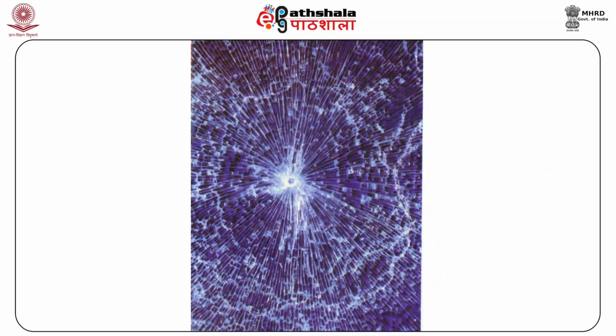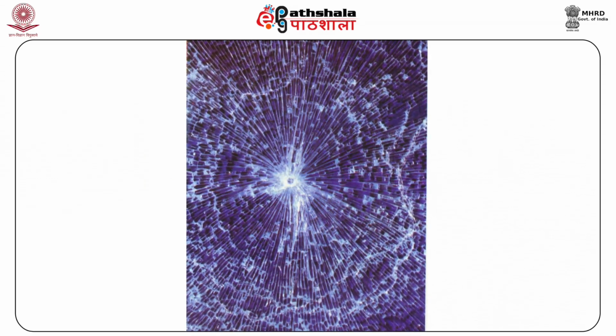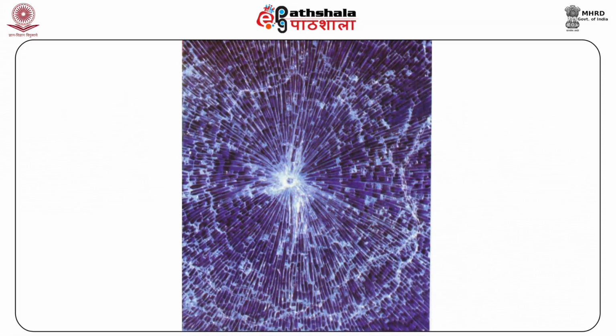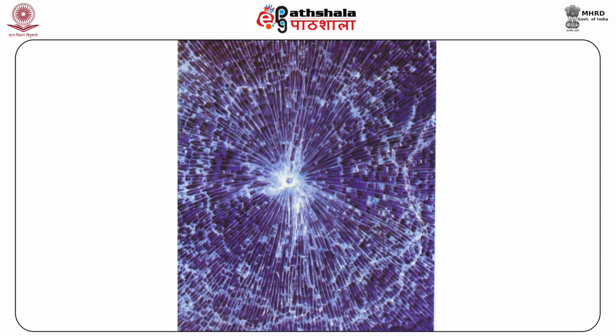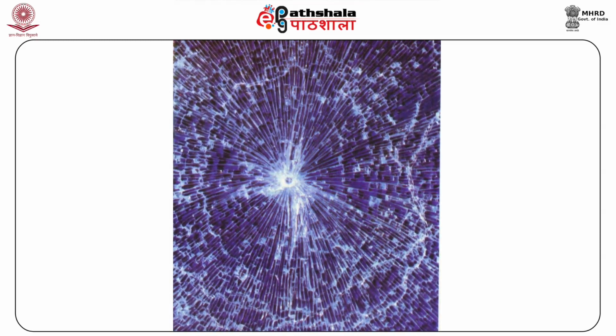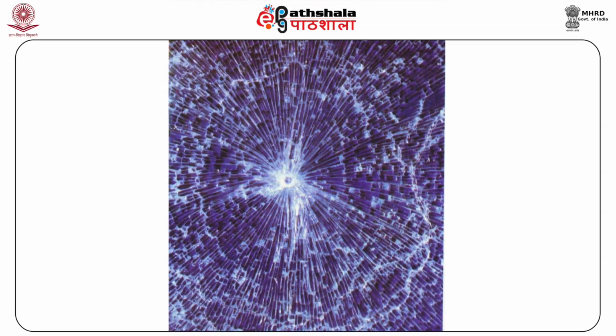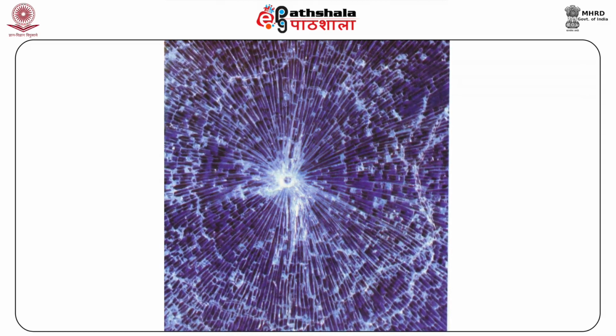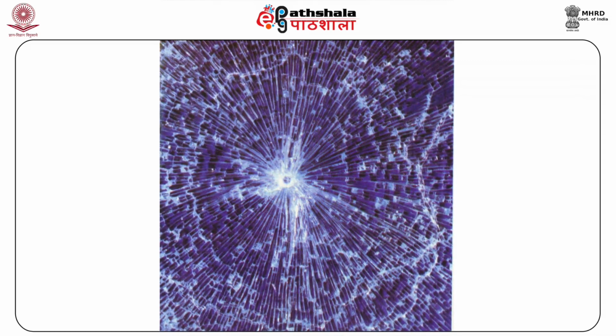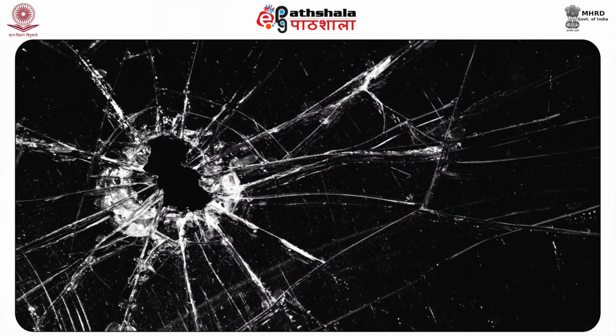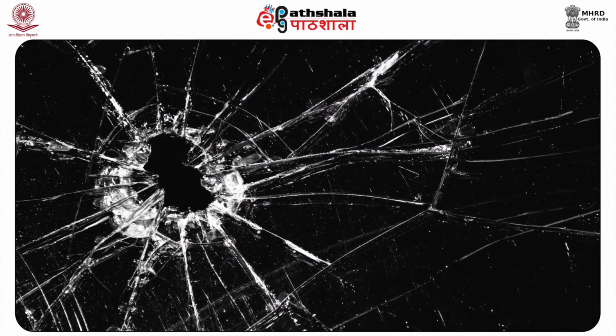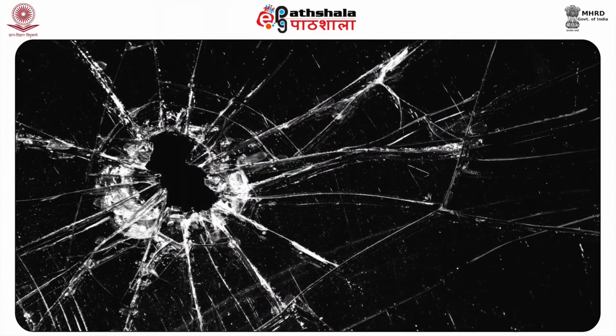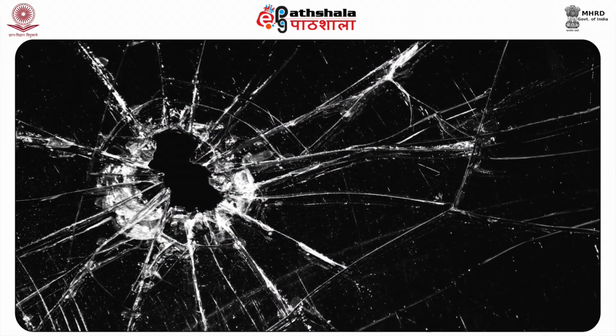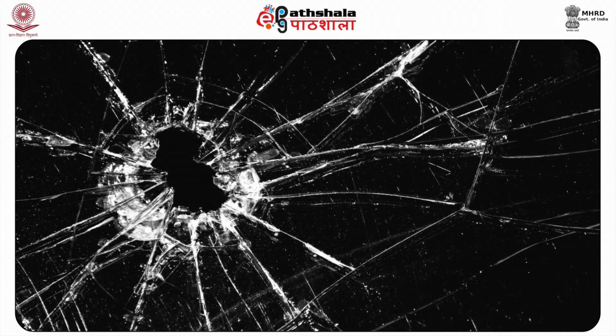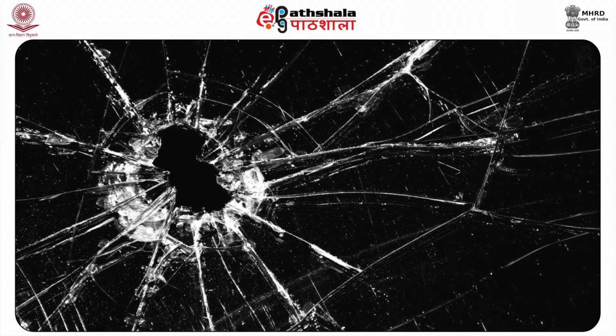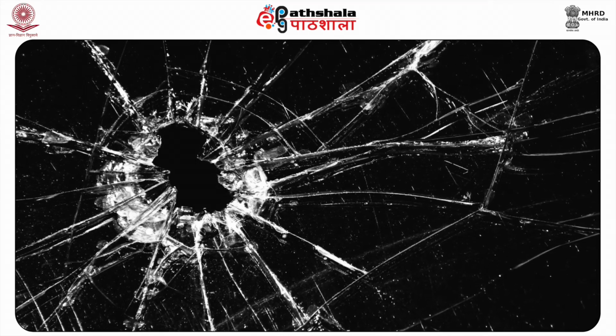Concentric fractures. But if the force continues even after radial fracture, especially when the instrument is either blunt or tapers abruptly, there is a bending movement that causes tensile stresses to develop on the side of the glass to which force was applied. This leads to a series of cracks known as concentric fractures, which connect with the adjacent radial fractures. The concentric fractures form a series of broken circles or arcs around the point of contact.